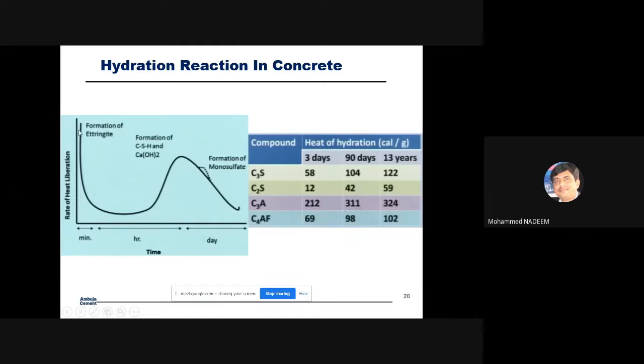And this is how the formation happens in the beginning. Because of the presence of gypsum, there will not be any reaction for about 2 or 3 hours, and later on the reaction happens like this. There will be a maximum heat of hydration in maybe 3 to 4 days, and then it gets reduced because now the tricalcium aluminate is reacted, C4AF is reacted, most of the C3S is reacted, and then C2S starts. So this is how heat of hydration is liberated in a concrete.